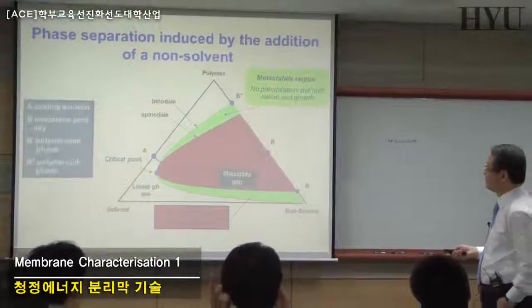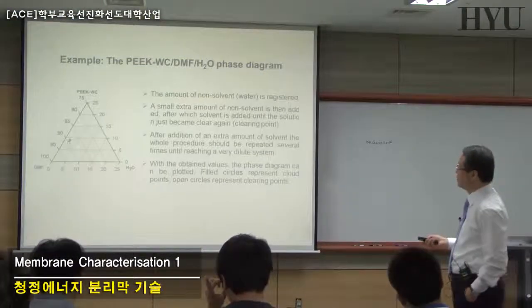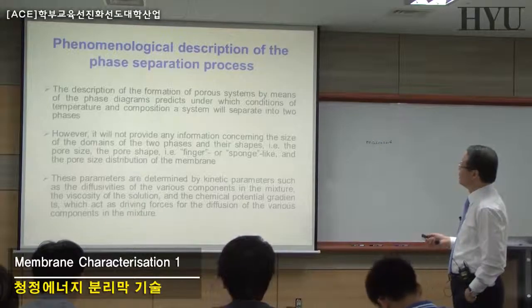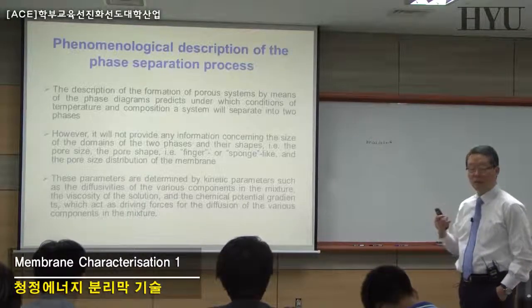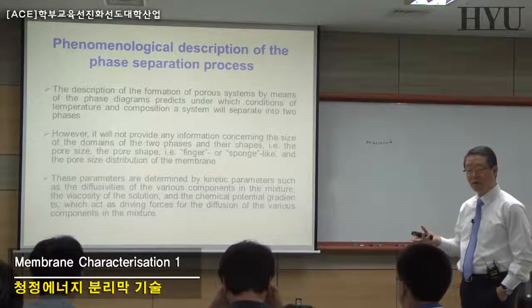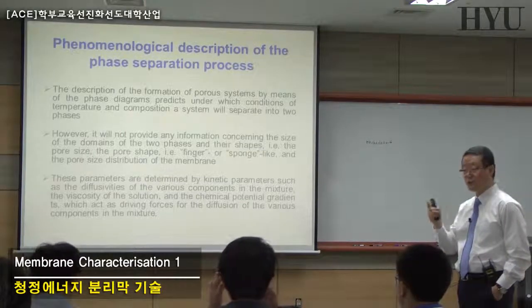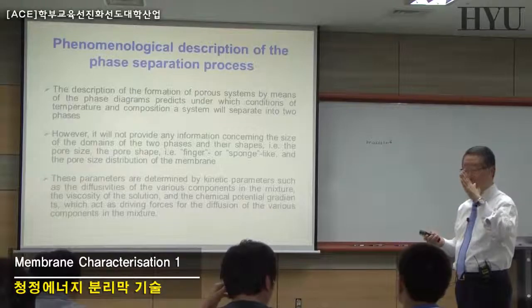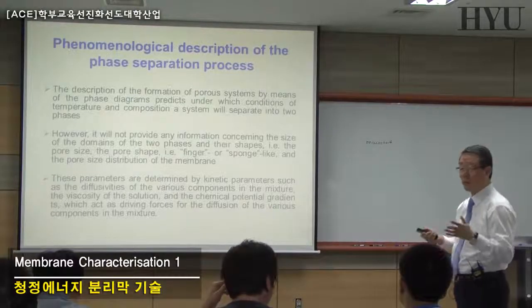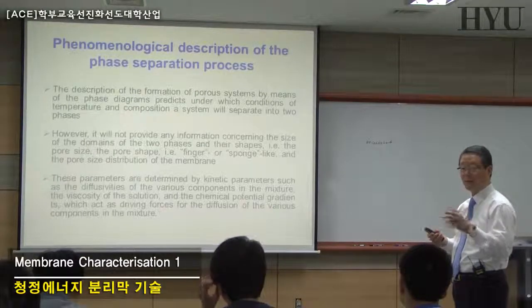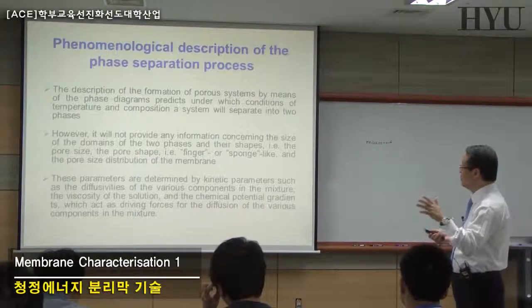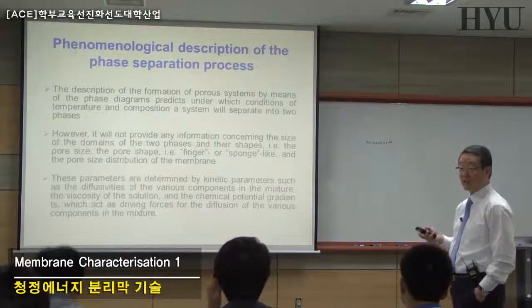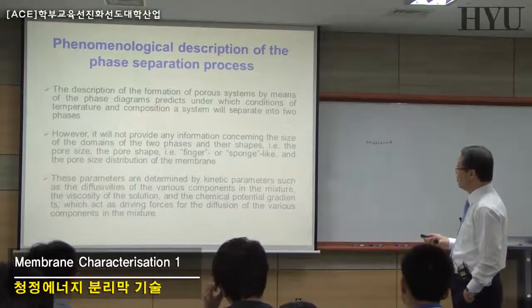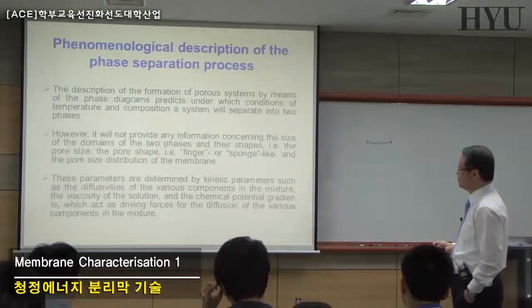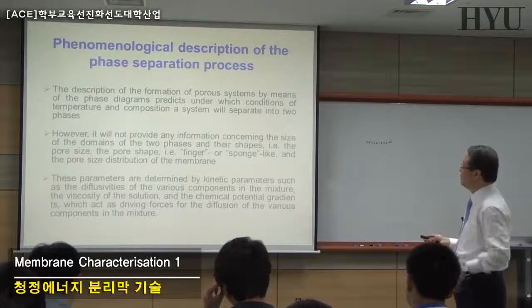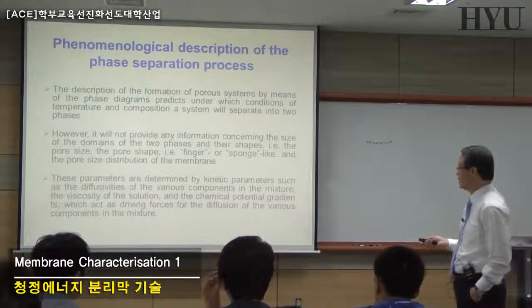So we have to think about those thermodynamic points. Usually you can make a macrovoid finger-like structure or sponge-like structure, or you can make a thin skin layer. Those are not exactly determined by where your point is, but you have to think about your kinetic parameters to finally pinpoint finger or sponge-like structures. So in addition to the thermodynamic factor, we have to think about the kinetic factors in this case.